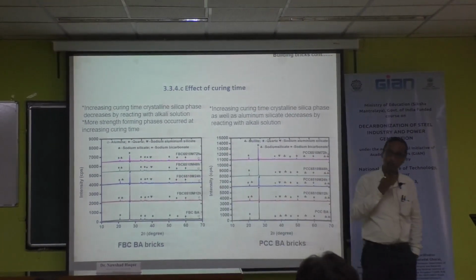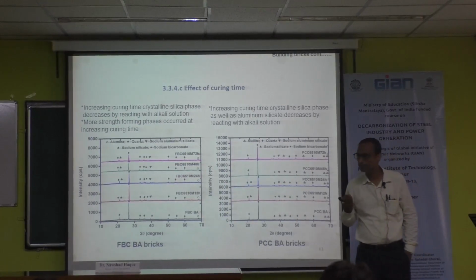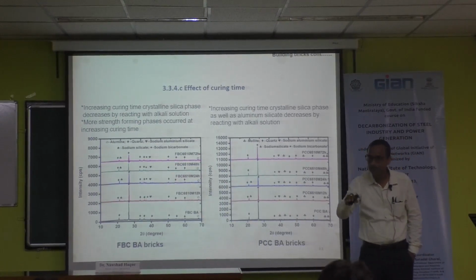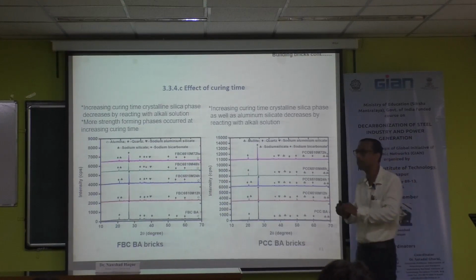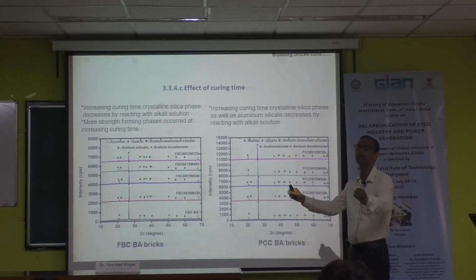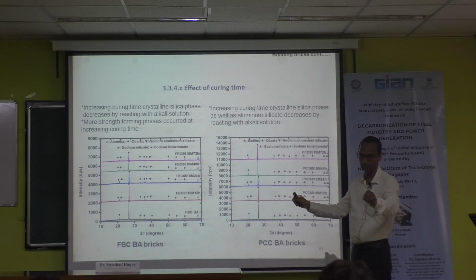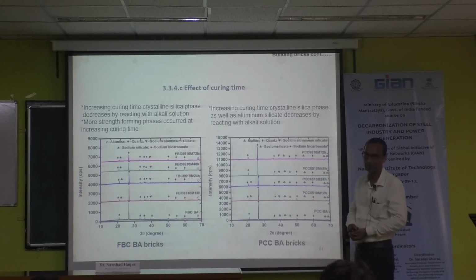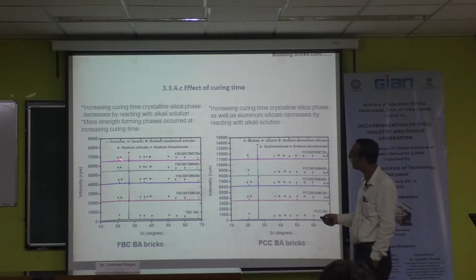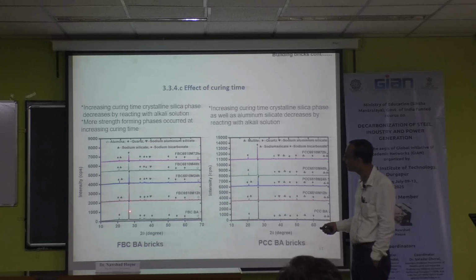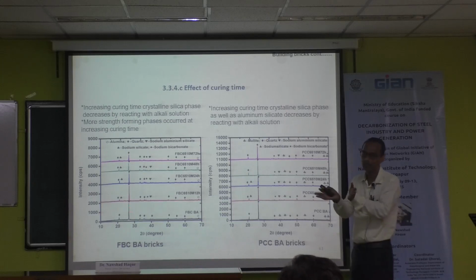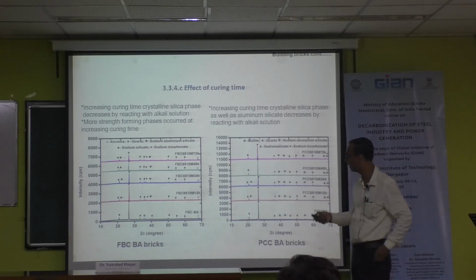How can you predict that geopolymerization is increasing? When this silica peak will gradually decrease. Here the peak is very short. Here you can see the peak is very high. It means this peak, the silica, a major amount of silica will dissolve and it will form the geopolymer. Okay, this is the indicator.